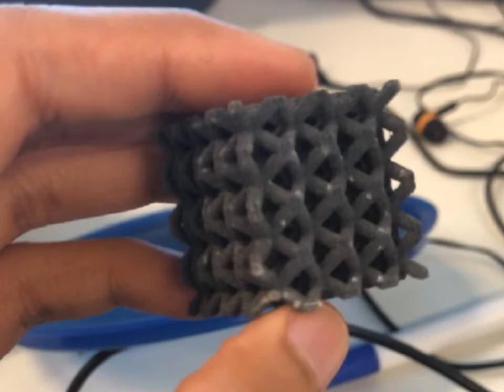So while we admire this image, we've seen that corrosion for aluminium alloys is deterministic, and I think it's probably fair to say that as a community we now get it. That knowledge has largely come from the last couple of decades, but now what's happening, as of today, is we're seeing that things like additive manufacturing can present new phases that we've not seen before, not studied. There's new levels of refinement. We have hyperloaded solutes and the possibility to create alloys that have never been made before in terms of the amount of solute we can add to aluminium, but also in the range and the combination of alloying elements that we can alloy with aluminium.